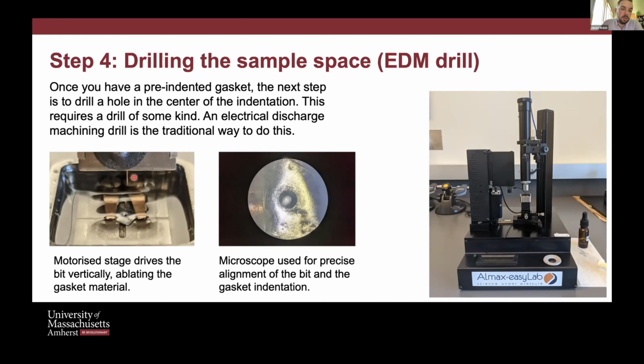We've actually got this working quite nicely. It does work repeatably. This is just a small copper wire, and there's a motorized stage here, or a motor that's moving this entire stage perfectly vertically. And then when it makes contact with the gasket, it will basically ablate the gasket material to the thickness of whatever wire you put on. And so this is another benefit of the laser drill, is that you can basically pick what hole size you want. With an EDM, you're limited to what you can purchase as a gauge for the wire that you're using. I'm not going into too much detail with this, but this is an important aspect of high pressure. You need to have a way to drill the sample space.